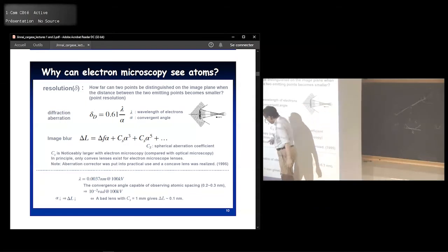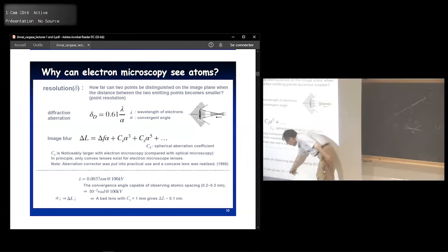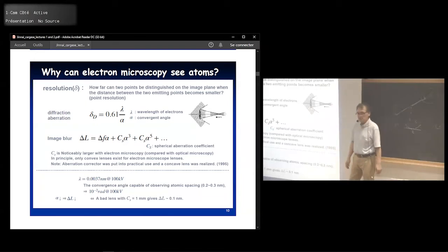And then, like I say, that the electron microscope lens is not good. This coefficient is something like 1 millimeter. And for the optical microscope, it's almost 0. Okay, and then even though the CS is large, we plug in here, and then this delta L, the blur, you can come up to a 0.1 nanometer. So that's why with the electron microscope you can observe the individual atoms. Okay. So the key point is that the short wavelengths, that's all.